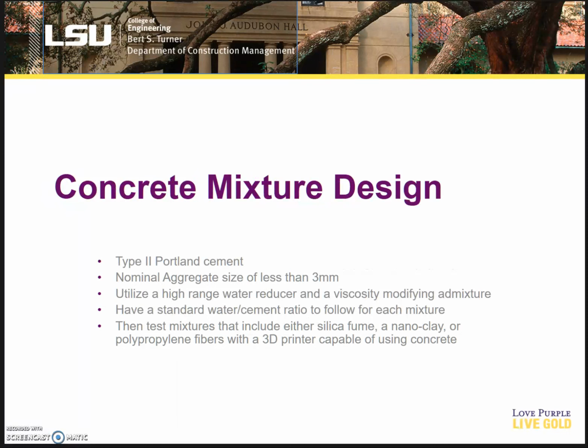For this experiment, our concrete mixture design, we'll have to further tweak it to get it just right, but it's going to use a type 2 Portland cement, nominal aggregate size of less than 3 millimeters. It'll utilize a high-range water reducer and viscosity modifying admixture to get the right consistency so it can be extruded.